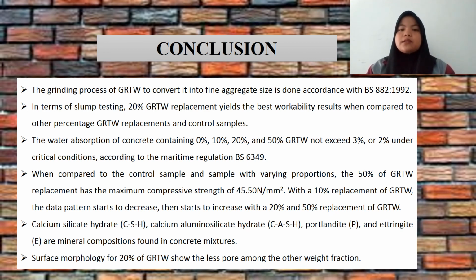When compared to the control sample and mixes with varying proportion, the 50% of GRTW has the maximum compressive strength. With a 10% weight fraction of GRTW, the data pattern starts to decrease, then starts to increase with 20% and 50% weight fraction of GRTW. Calcium silicate hydrate, calcium aluminosilicate hydrate, portlandite and ettringite are mineral compositions found in the concrete mixture. Surface morphology for 20% of GRTW shows the fewest pores among the other weight fractions.